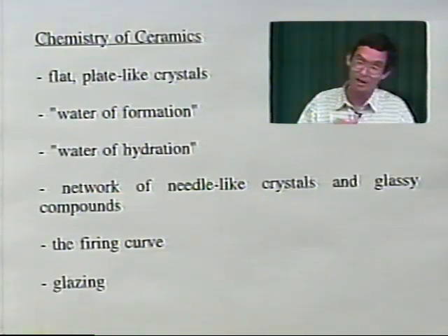So what you have to do is heat up the product very, very slowly at the beginning and then hold it for a while at a particular temperature where the water starts coming out of the crystals, so it comes out really, really slowly. If you heat it up past that critical temperature, all the water will come out of the crystals very quickly, and you'll have the steam cracking the product. So you have to hold it at a particular temperature for a long time.